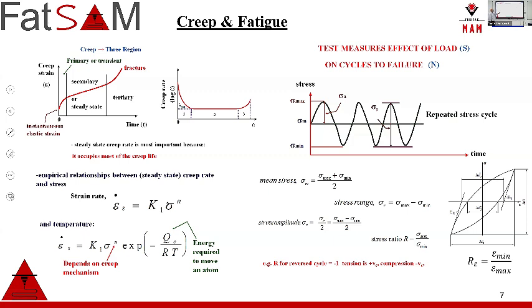One of the most important parameters is critical resolved shear stress in the second stage of creep, because if critical resolved shear stress is higher, it means you have less plastic deformation at high temperatures and, not necessarily, but mostly, longer life cycles. In terms of fatigue, it's a kind of crack formation, and depending on the cyclic loading you applied, you can figure out crack initiation, then crack propagation, and the end of life cycle.